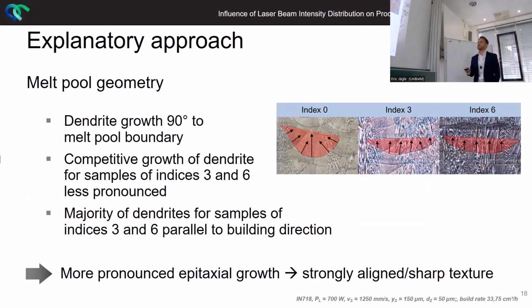And our explanatory approach was to have a deeper look at the dendrite growth, because it always occurs on the shortest way from the coolest to the hottest point, so in a 90-degree angle from the melt pool boundary to the center. And indeed, the melt pool shapes were different, deep and not that wide for samples of index 0, whereas the melt pool shape for index 3 and index 6 was much wider and flatter, leading to less competitive growth of dendrites for those samples, which leads to a strong epitaxial growth over many layers, so that we get a sharp texture.